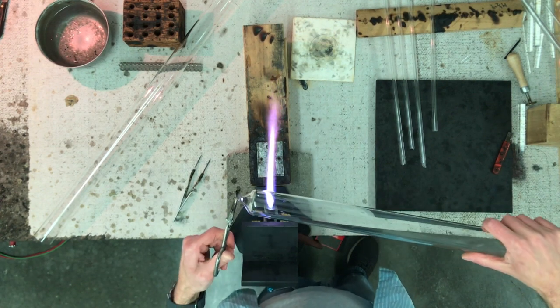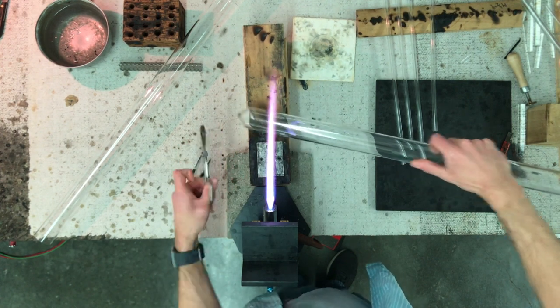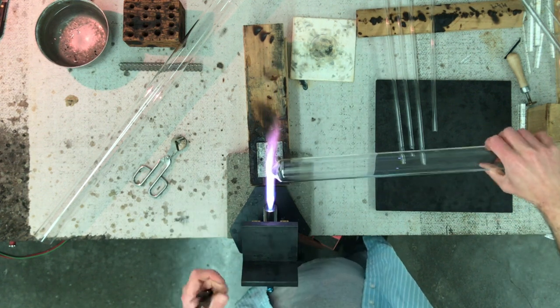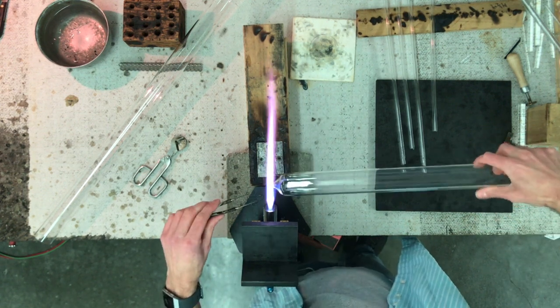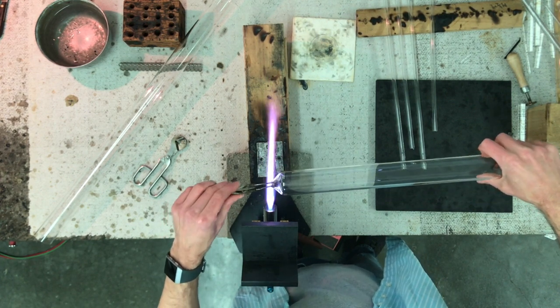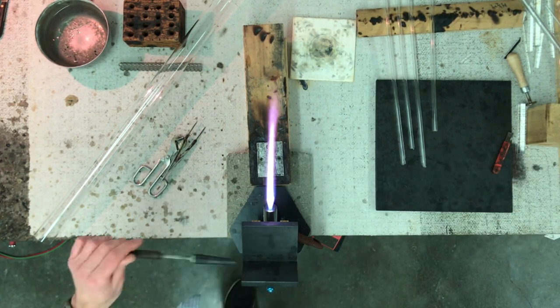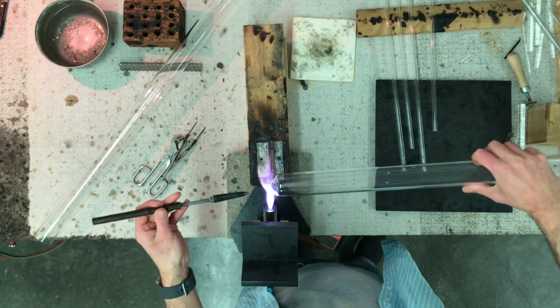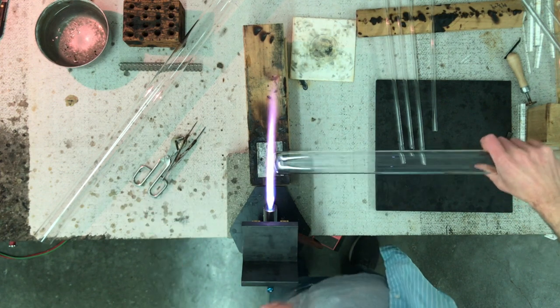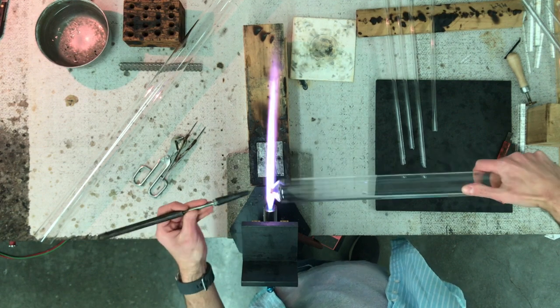And then I've got my diamond shears there, and you can heat up that little end. When you use the diamond shears, you want to come in slow and turning, and then you can tap that off. If you come in too fast with the diamond shears, you'll just pinch it closed, and you'll end up having to pull it out and do it over again. So you want a sort of stiff taffy consistency before you really start squeezing down on those diamond shears, or you're just going to pinch the opening closed, and then when you tap it off, you won't have a hole.